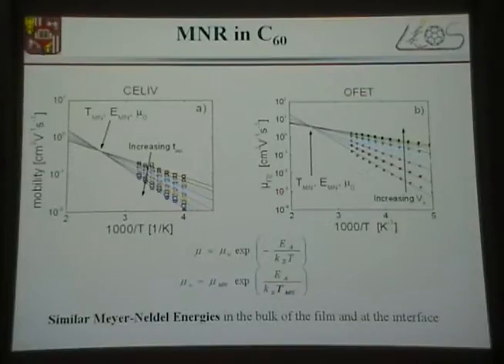it has been seen that in polymers the mobility dependence does not follow the Arrhenius plot. It actually follows a 1 over T squared plot, and there's the whole theory from Bässler, which explains why that is so, the models explaining the experimental data, which are very nice. But here we've only shown the so-called Meyer-Neldel rule, which is some sort of a method demonstrating the level of disorder in the film.